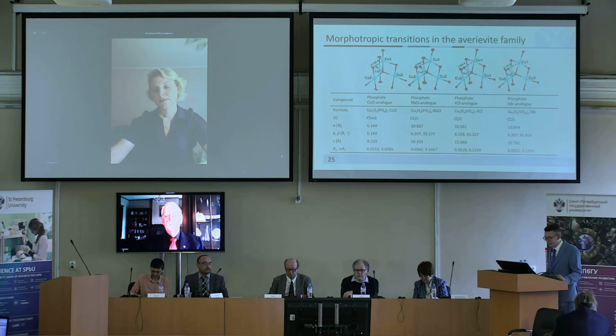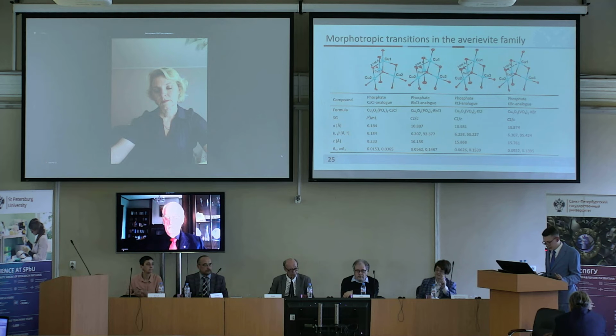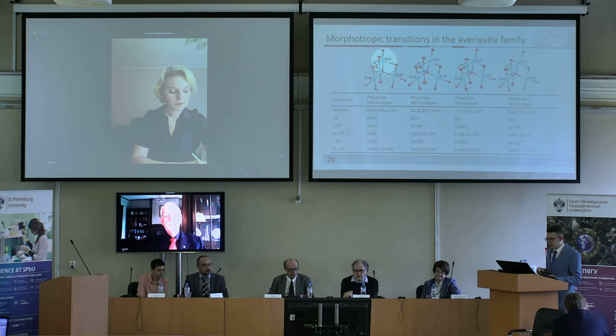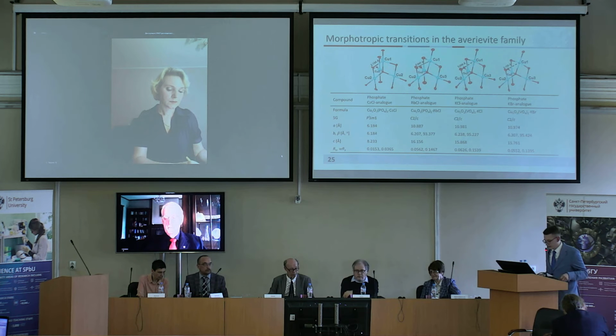When the vanadate tetrahedron is replaced with phosphate tetrahedrons, the structural rearrangement becomes more noticeable. The coordination geometries of copper are significantly distorted, which is especially evident in the example of the copper-1 atom. In the cesium chloride phase, it occupies the trigonal bipyramid. In the rubidium chloride phase, it becomes distorted, and in the potassium phase, it's rather a square pyramid.